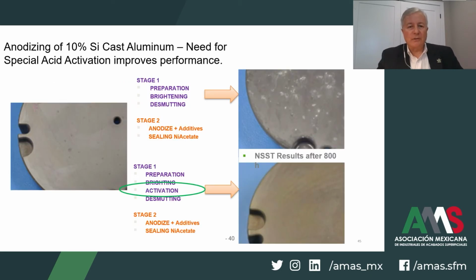As shown in this slide, with the anodizing of 10% silicon without activation, the importance of stage 1 steps are considered. In the top example, the traditional cleaning with a non-etch cleaner, brightening chemistry, and desmutting followed by the anodizing does not produce a good result after 800 hours exposure to neutral salt spray.